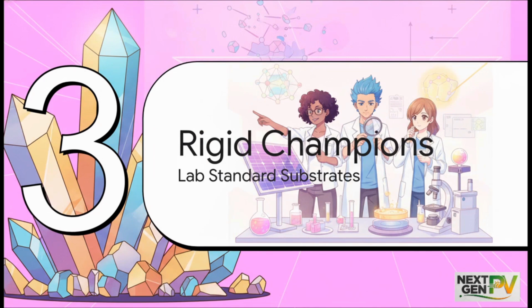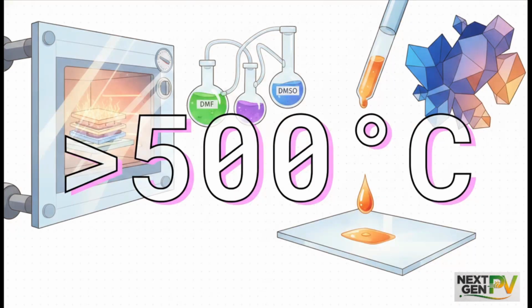Okay, section 3. Let's talk about the rigid champions. The undisputed heavyweight champion of the research lab is, without a doubt, rigid glass. Usually, it gets coated with a transparent conductive oxide, stuff like FTO or ITO, to carry the electricity out of the cell. But look at that thermal limit, over 500 degrees Celsius. That is huge. It lets engineers bake crucial electron transport layers, like titanium dioxide, at extreme temperatures to get these absolutely pristine crystal structures. Plus, glass is perfectly clear, wonderfully flat, and totally immune to harsh chemical solvents like DMF and DMSO that are used to dissolve those perovskite inks.